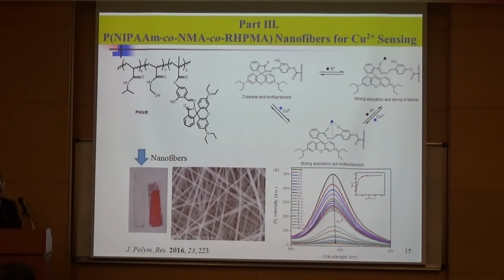The sensing mechanism for the rhodamine-based moiety is through a spirolactam ring-opening process. Before the addition of either proton or copper ion, this moiety is colorless, without absorption in the visible region, and also shows no emission, no fluorescence. After protonation, the ring is open and this turns on strong absorption, pink in color, and also strong fluorescence intensity. However, if combined with a copper ion to form this complex, it will only show strong absorption, pink in color, but the fluorescence will be quenched due to the paramagnetic effect